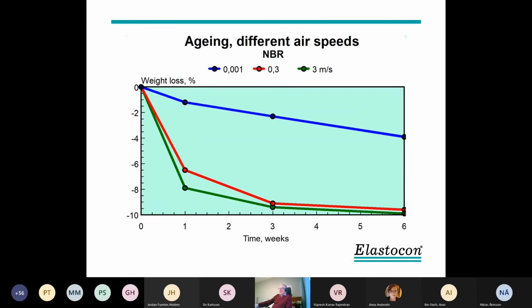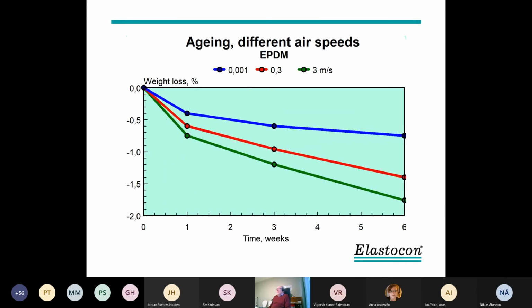If we look at another material, EPDM, there we lose much less because the softener is much less volatile. But we still see the difference between the air speeds: we lose more at higher speed. And losing softener and also antioxidants, of course, changes the hardness and the tensile strength and all other properties as well.